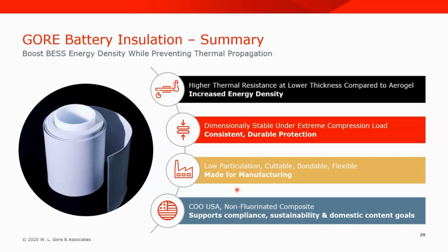We believe that it has a tremendous value in a range of applications, and that's based on its ability to increase energy density. It offers a higher thermal resistance, especially at a lower thickness, and it is dimensionally stable under extreme compression load, and that provides a consistent and durable protection. As you've shown in the video, it's very low particulating, it's cuttable, it's bondable, very flexible.